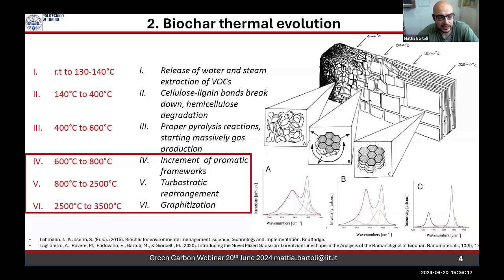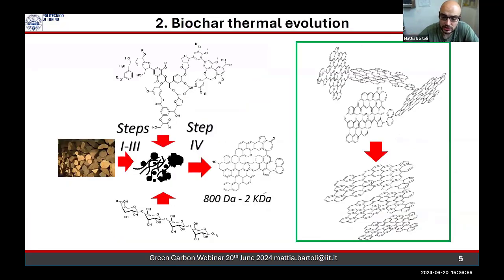if you discuss with someone who says that you can fully graphitize biochar at 2000 degrees, it's not completely true, because, again, a little bit more science on that, if you start to heat it, you reach a point where you cannot push the graphitization process further. According to the pioneering study of Rosalind Franklin in the middle of the 20th century, biochar is not a graphitizable carbon. It can be highly ordered, similar to graphite, but it will never be a graphite. So for certain kinds of application, conductive biochar is not the best, for the simple reason that, as you can see here, the intrinsic complexity of the starting biomass prevents the full reorganization into proper graphitic structure.